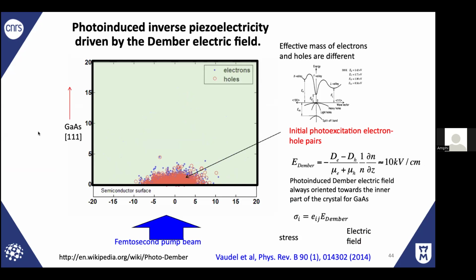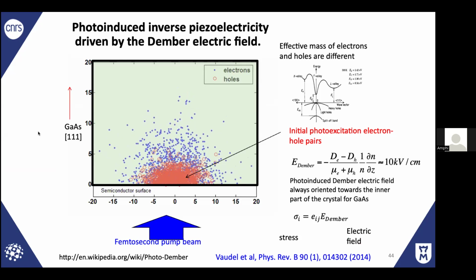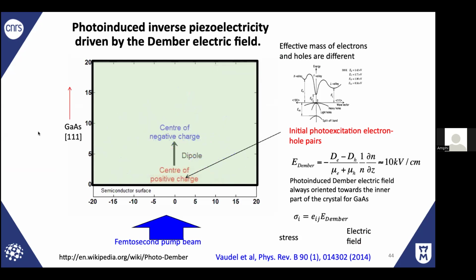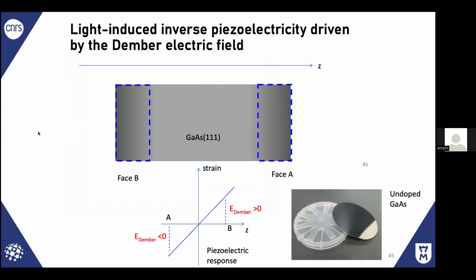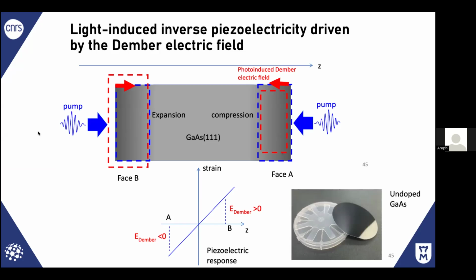This Dember electric field is related to the diffusion coefficient and the mobility. In gallium arsenide, we can typically reach an electric field of 10 kilovolt per centimeter. And then we look at the coherent acoustic phonon emission through the Dember effect. We have such a sample, and we shine light on one side or the other side. If you look at the theory on face B or face A, when you shine light you create a Dember field, but these directions are non-equivalent because this is a non-centrosymmetric material. In one case, you create a positive electric field, so you have a positive strain. In the other case, you create a negative electric field. So according to the z-axis, you induce compression. This is exactly what you expect: expansion, compression, and exactly what we observe.